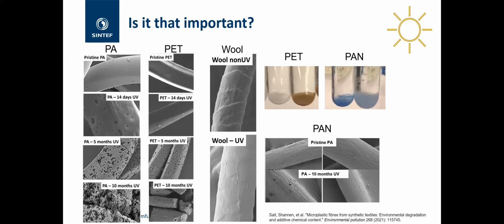We saw the same for the polyamide. It was even more sort of surface changes. We're getting really big changes in the morphology of the surface. And if we're starting to think about toxicology, it's the surface of particles that organisms are interacting with. These are quite fundamental changes. Of course, it's not the same for all polymer types necessarily. So the polyacrylic, which is the bottom right, you can see after 10 months, there was virtually no change, just maybe the start of some evidence of degradation.